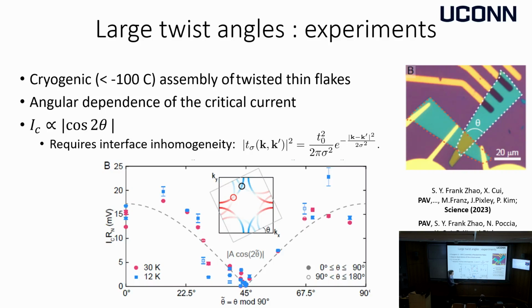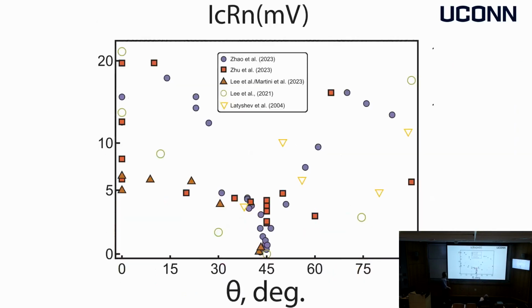Indeed, the critical current goes pretty quickly down, and it becomes very small around 45 degrees. What we did recently was assemble all the data from the literature available to this day. The empty symbols correspond to the samples that had to be annealed. You can see that they're kind of scattered a bit, so it's hard to say. The samples from Philip Kim's group that I've shown you are the purple ones, and they nicely go down at 45 degrees. But for the other groups, if you look, there's quite a bit of a spread in the data still up to this day.